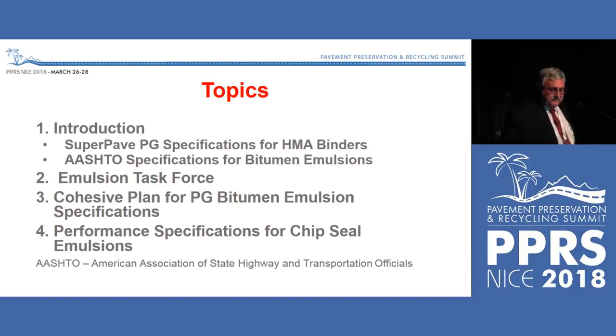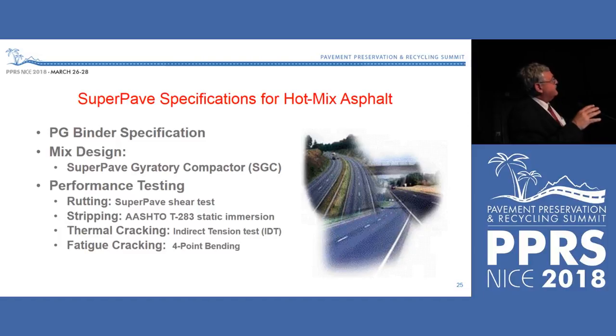Please refer to this. So with that, the Superpave, of course, has a PG binder specification, and that's what we're really trying to replicate primarily, but recognize we're also trying to do all the other things that are part of a performance system, that is the mix design requirements and the performance testing. In the case of Superpave, the mix design uses a SGC gyratory, taken much from the French system with the press gyratoire. The performance testing, initially it was rutting, stripping, thermal cracking, fatigue cracking.